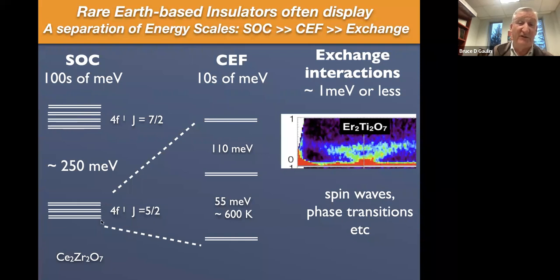So there's 2J plus 1, 6 states in that multiplet, and they're separated from the next excited states, the J equals 7/2 spin orbit coupled state, by about 250 millielectron volts. And actually, we can probe that spectroscopically with neutrons, and I'll show you that in the next slide. And then you can step down in energy, and you can look at the splitting between these 3 doublets that make up the J equals 5/2 multiplet. These are split by crystalline electric field effects, which are weaker than the spin orbit coupling by about a factor of 10. Here you get splittings between these doublets that are of order 50 meV or so.